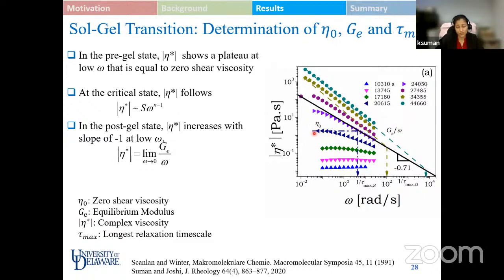Now with the low frequency asymptotes drawn, we intersect them with the critical gel state line, which is a power law behavior with an exponent of n-1, n being identical to that observed in the previous slide using the Winter criteria. The intersection of this leads to some value of omega. The inverse of this omega value gives us the longest relaxation time scale of the material in the pre-gel and the post-gel state. So this is an important diagram: from a single experiment, with multiple frequency sweeps, and using eta star values at different frequencies, we are able to get 4 parameters, which are eta naught, G_E, and tau max, the longest relaxation time scale in the pre-gel and in the post-gel region.